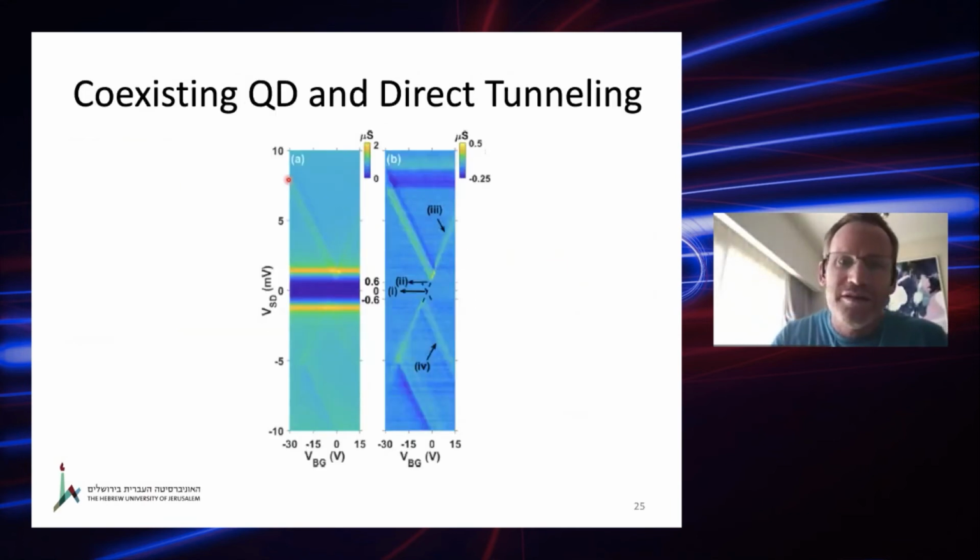Now, this is the total signature, VSD versus backgate, and you see that this is the niobium diselenide gap, and you see these diagonal features over here. And these diagonal features are just a single replica of a Coulomb diamond, and if I subtract a constant background, I see very well these slopes of the truncated Coulomb diamond with a gap that appears here.